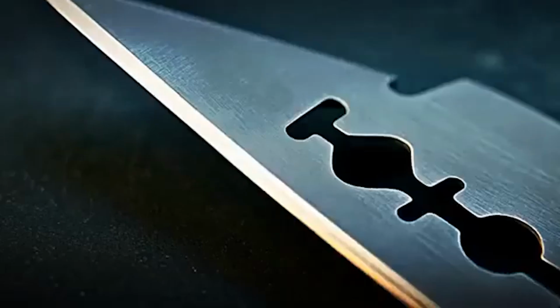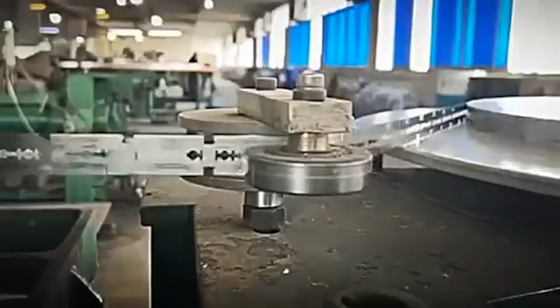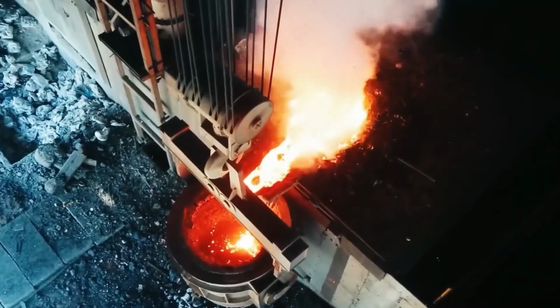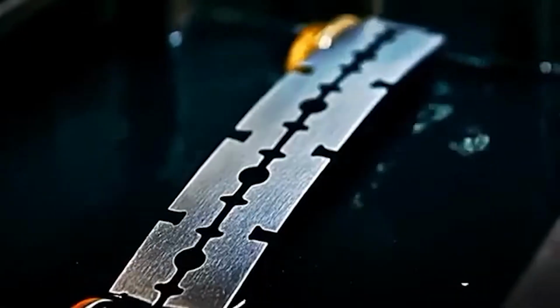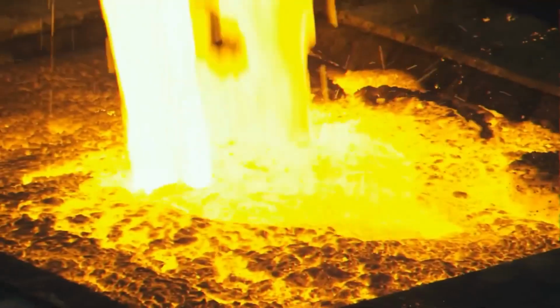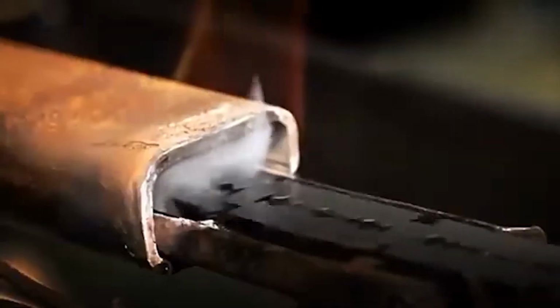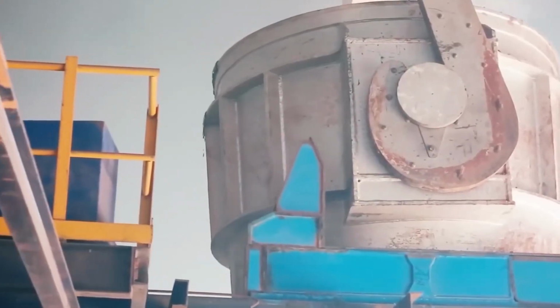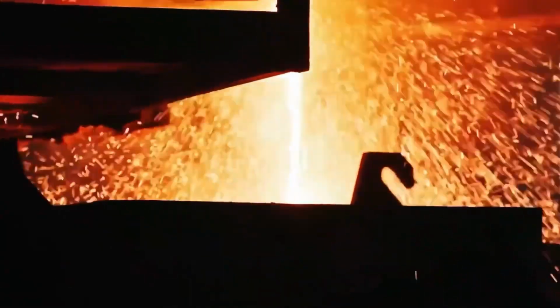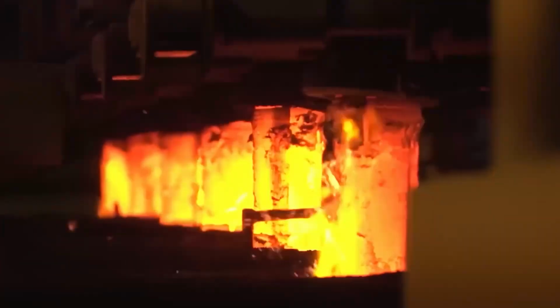accumulated during quenching, lowered brittleness to acceptable levels, and brought final hardness down to a range of approximately 58 to 62 HRC, hard enough to hold a sharp edge through multiple shaves and flexible enough to survive being clamped into a razor without fracturing. Throughout both heat treatment stages, blade flatness was monitored carefully, as thin steel at elevated temperatures had a reliable tendency to warp in ways that no amount of subsequent grinding could fully correct. Once the tempering cycle was complete, the blades emerged from the furnaces ready for the operation that would finally make